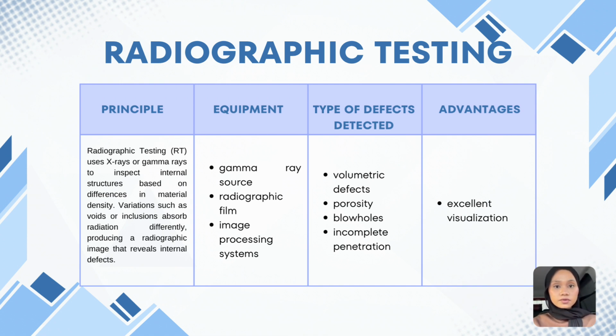RT is mainly used to detect volumetric defects such as porosity, blowholes, and also incomplete penetration, especially in welds. These defects are difficult to see from the surface but can be clearly identified using the radiographic image. One of the major advantages of radiographic testing is that it's excellent for visualization. It will provide a permanent record of inspection results and also allow the inspectors to clearly see the size and shape of internal defects.